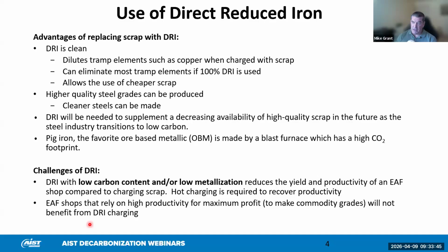Now, there are challenges with DRI, especially with low metallization. Martin mentioned 99% metallization for hydrogen-based DRI. Typical commodity-based DRI is around 94% metallization. Many of these DRIs have relatively low carbon content, so the yield and productivity of the electric arc furnace is reduced, whether using high metallized DRI or low metallized DRI.